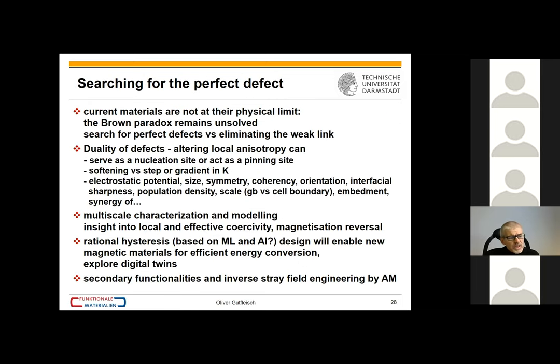That is my summary slide. We have the duality of defects. We alter local anisotropy. So the bad guys would serve as nucleation sites. Good guys would basically act as pinning sites.